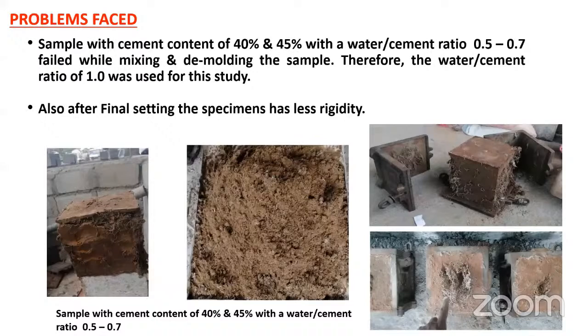Problem faced. Samples with cement content of 40% and 45% with water-cement ratio of 0.5 to 0.7 failed while mixing and demolding the sample. Therefore, a water-cement ratio of 1.0 was used in this study.